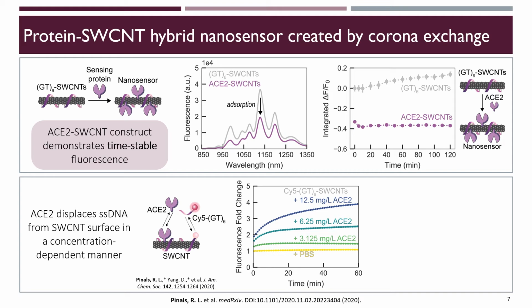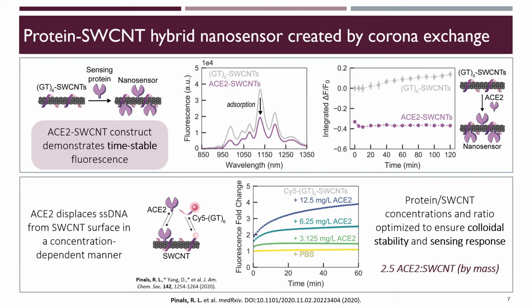Now I'm showing that ACE2 adsorption displaces DNA from the carbon nanotube surface, as we hypothesized, in a concentration-dependent manner, as we might expect. Although it may seem that we want to maximize the loading of this sensing protein onto the carbon nanotube surface, I also aim to balance this with other nanosensor properties. To this end, both the absolute values of the concentrations and the ratio between the concentrations of protein and carbon nanotube were optimized, and this yields a mass ratio of 2.5 ACE2 to carbon nanotubes. Interestingly, this ratio was in very close agreement with our footprint calculation as an estimate and was further refined by this experimental optimization.